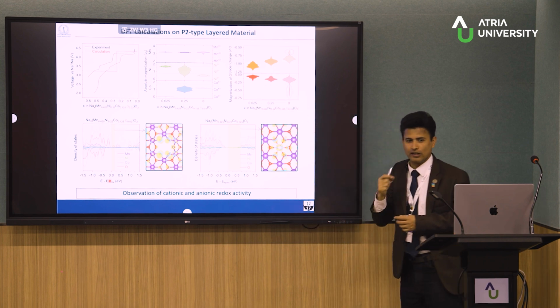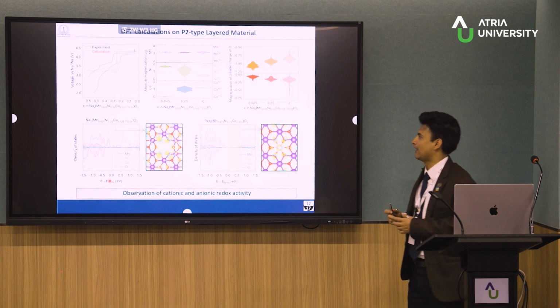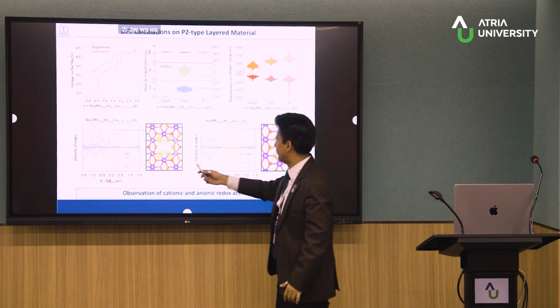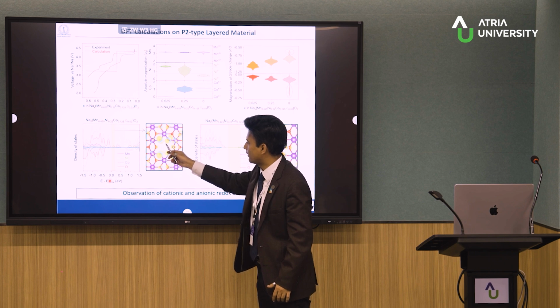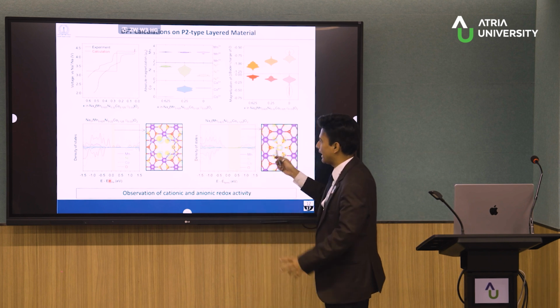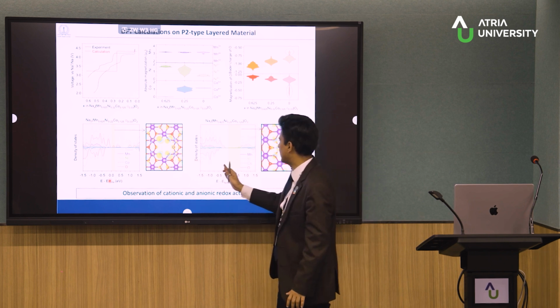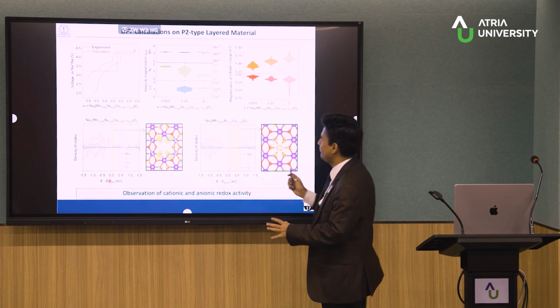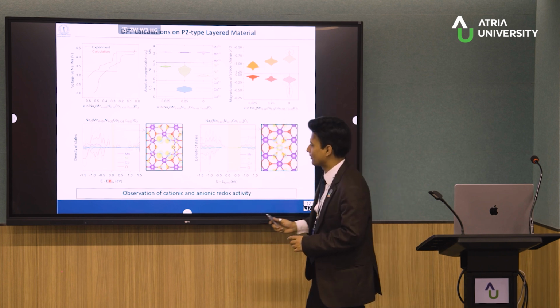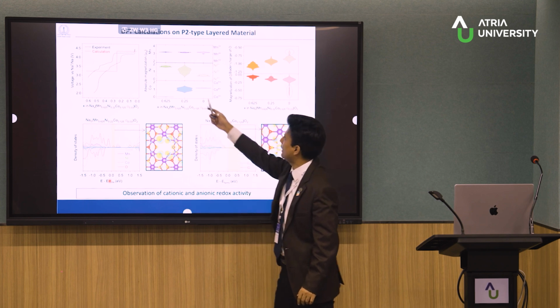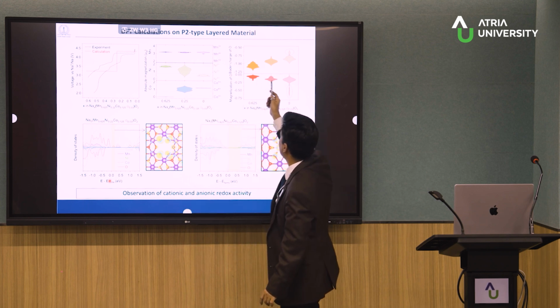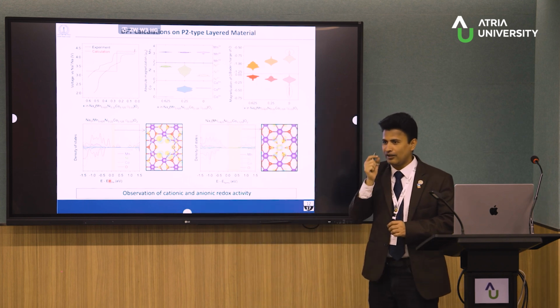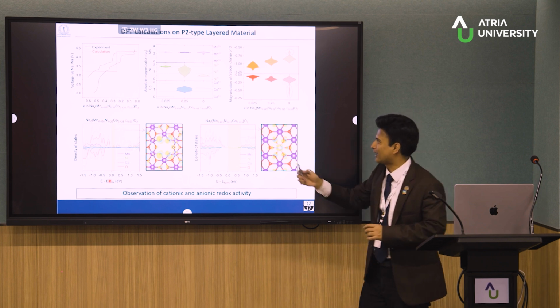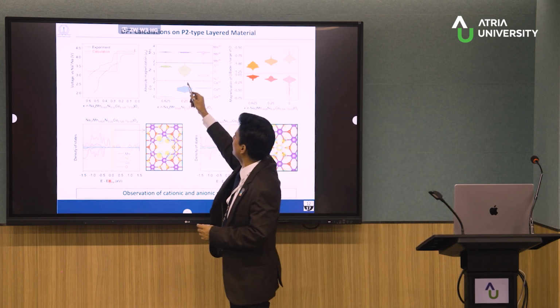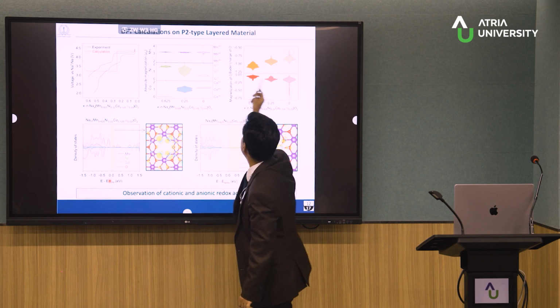So this is a wonderful proof from theory that there is anionic redox. And if there is a hole in the transition metal, or if there is no hole, accordingly, we can see the local band gap, everything changes. And in principle, we can say from DFT also there is observation of both cationic redox with the nickel cobalt and anionic redox. Now cobalt is only 10%. Yeah, so the capacity contribution is very little. Most capacity comes because of the nickel and oxygen.